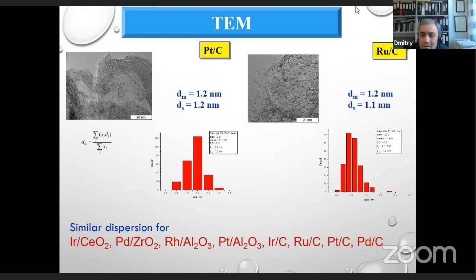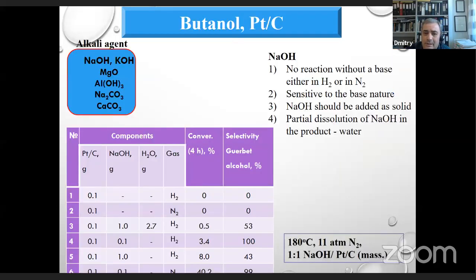As you can see from the size of metal clusters, they were in the range of approximately a little bit higher than one nanometer. Different types of alkali agents were tried: sodium hydroxide, potassium hydroxide, then MgO, aluminium hydroxide, sodium and calcium carbonates. It turned out that only two alkali agents were efficient, sodium hydroxide and potassium hydroxide, and the majority of experiments were done using this type of catalytic system: metal on a support, and then dry sodium hydroxide, which was introduced into the reaction mixture.